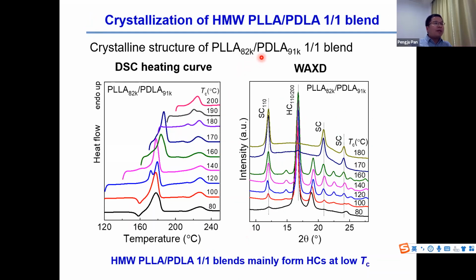However, the high molecular weight PLA and PDLA blend shows a much different crystalline structure from the low molecular weight one. We used a high molecular weight blend, where the molecular weight of PLA and PDLA is higher than 80,000. We crystallized the blend in a wide temperature range from 80 to 200 degrees C.